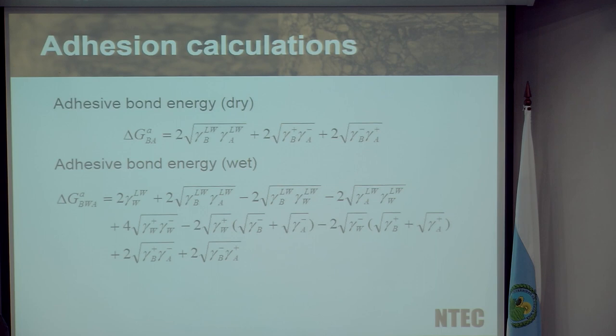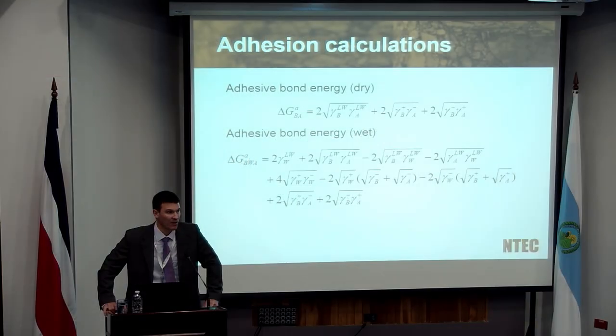And I say, in an asphalt mixture, we've got our bitumen and we've got our stone, but in terms of moisture damage, we're also now going to add water. And if we add water, and obviously we know its properties in terms of its surface energy, we find that we can determine what we would call the wet adhesion, or more correctly, the debonding adhesion, or the debonding energy. Those results on their own, again, would give you some indication.